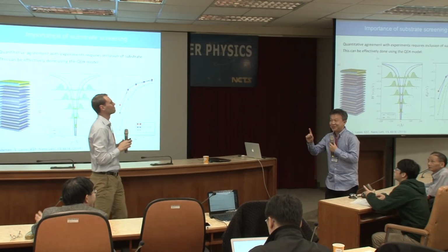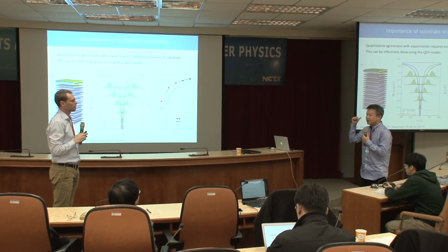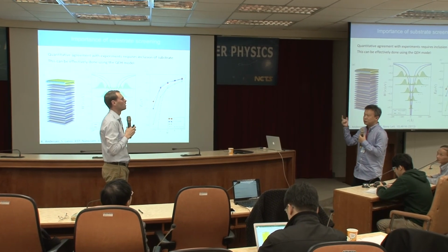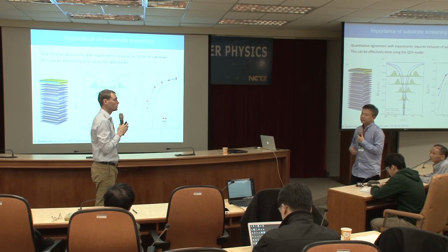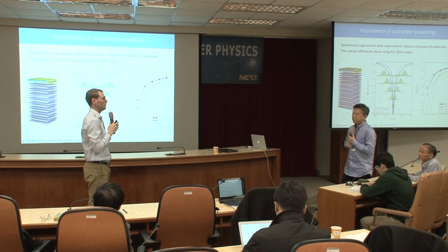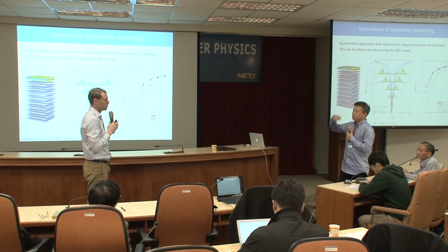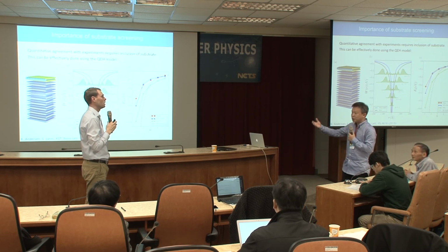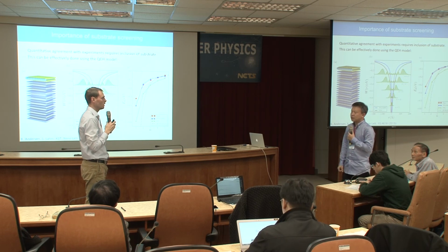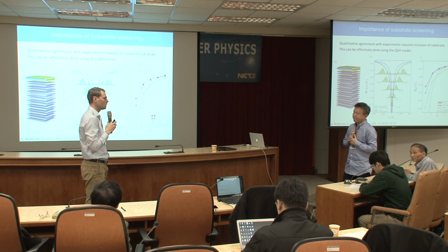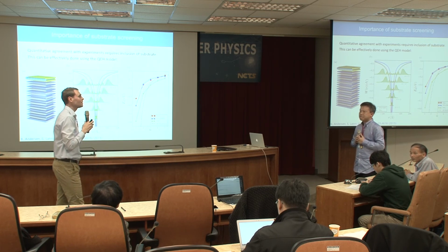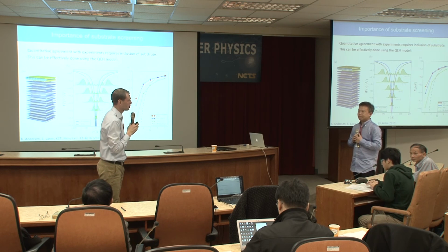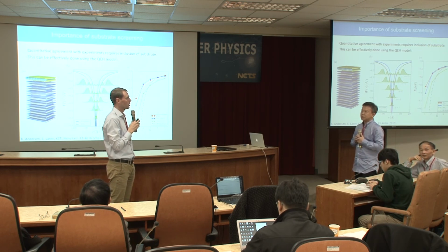Okay, so I have one minor question. You mentioned you deal with the vertex. So that means with GPAW or any package you use, you can really do the fully self-consistent GW and not just beyond the GWA. This is not self-consistent GW. This is non-self-consistent G naught W naught. Yes. Starting from PBE typically. Yes. But we include the vertex. But if you really go through the whole thing, you can approach the fully self-consistent GW. We can. Yes. And we have tried that, updating the eigenvalues only. Yes. That's pretty robust. That works. You can get energies out. How about the Green function? The Green function, the student didn't succeed. But we had a project trying to do this quasi-particle self-consistent implementation. But it's not there in GPAW for now.